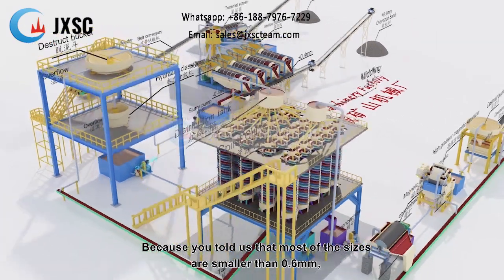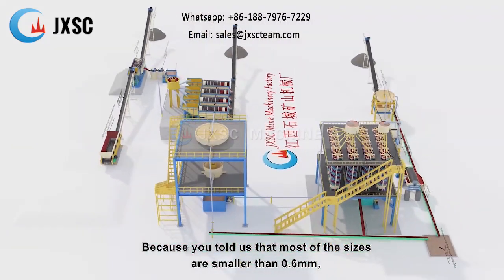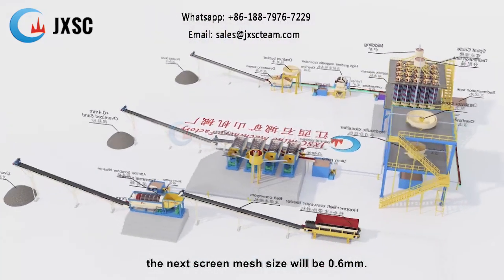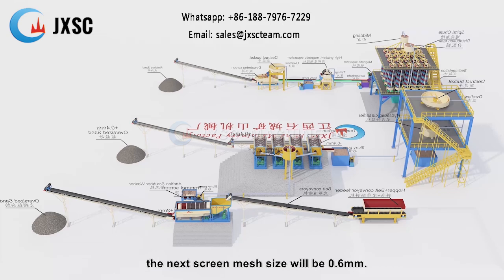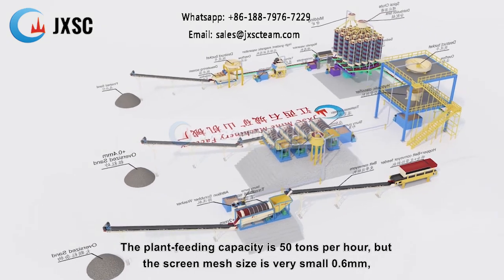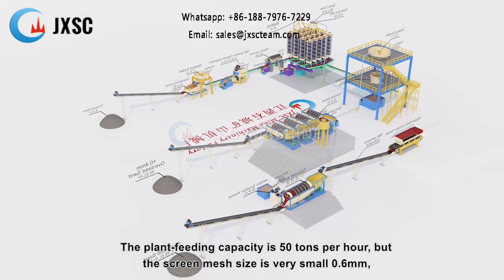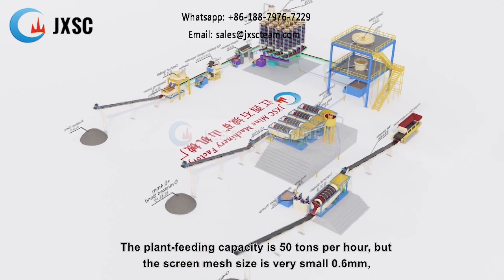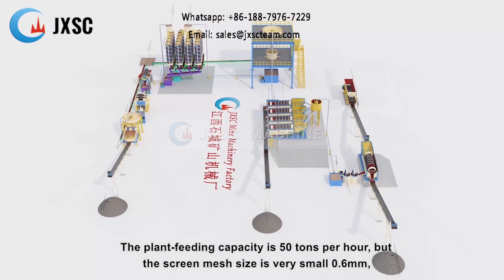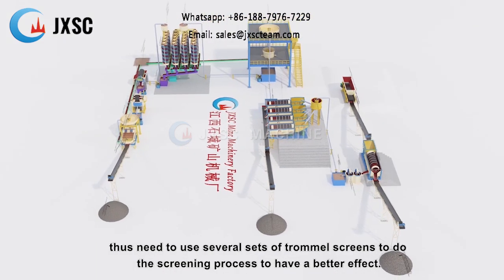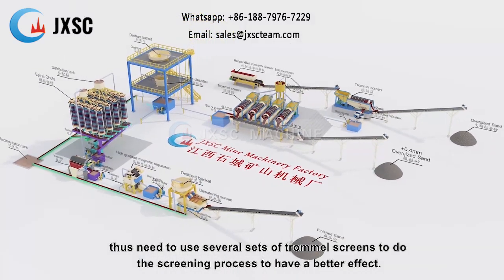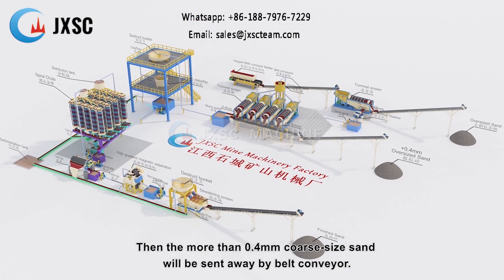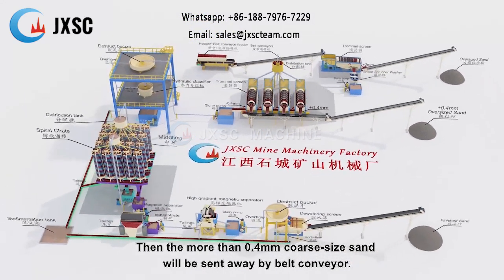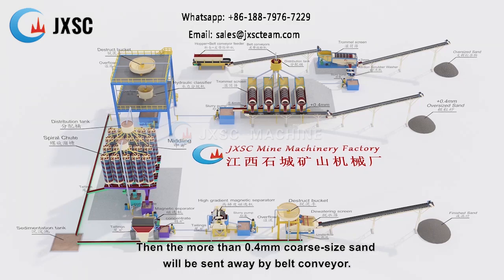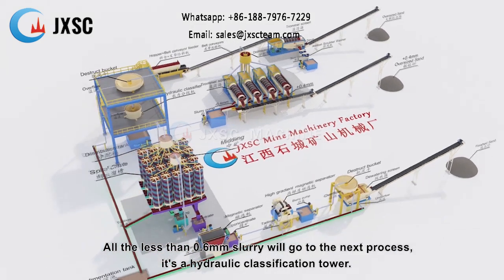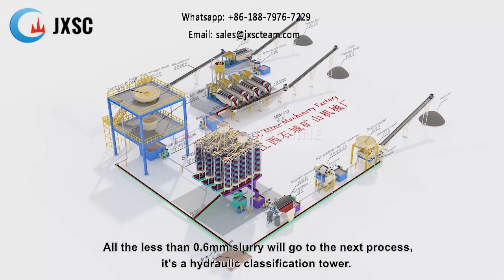Because you told us that most of the sizes are smaller than 0.6 millimeters, the next screen mesh size will be 0.6 millimeters. The plant feeding capacity is 50 tons per hour, but the screen mesh size is very small, 0.6 millimeters, thus we need to use several sets of trommel screens to do the screening process to have a better effect. Then the more than 0.4 millimeter coarse size sand will be sent away by belt conveyor. All the less than 0.6 millimeter slurry will go to the next process.